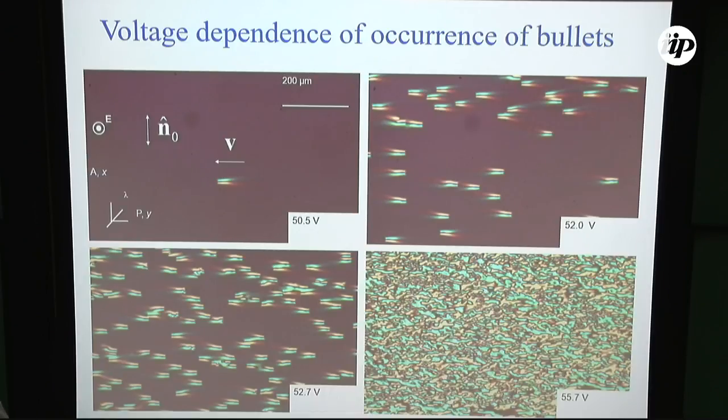So if you have some conductivity, then it's like a Rayleigh-Benard thermal instability only caused by the motion of ions through the viscous medium that produces stripes. And these stripes are kind of visible here. It's a chaotic pattern of stripes.